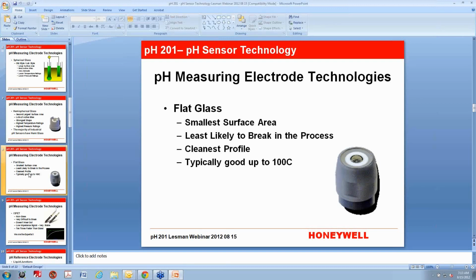The reason for that is, again, that weld line where the actual pH-sensitive glass is welded to the stem wear. And that weld angle is 90 degrees, and that is going to be the weakest of the weld angles. So at a high temperature, when the fluid behind that glass starts to volatilize, when you get over the boiling point, that can actually cause it to break right along that weld line. And this is pretty typical for what I would consider good quality pH-sensitive glass. That kind of runs across the board for most manufacturers.